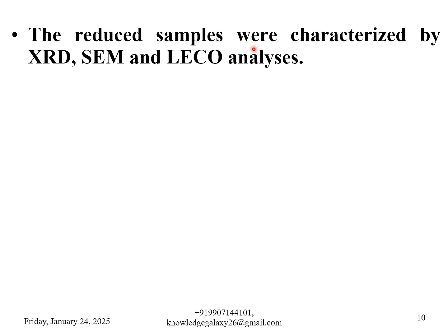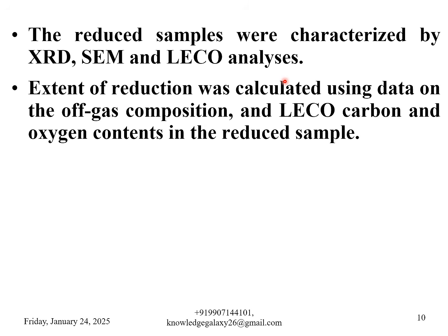The reduced samples were characterized by X-ray diffraction, SEM and LECO analysis. Extent of reduction was calculated using data on the off-gas composition and LECO carbon and oxygen contents in the reduced samples.